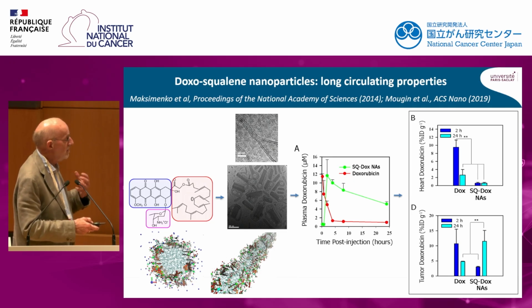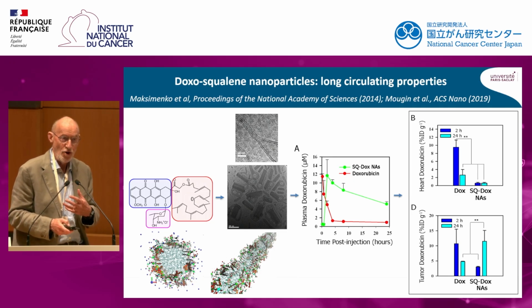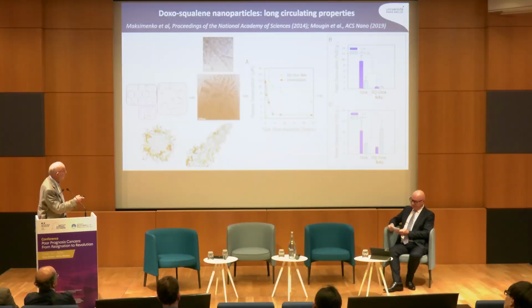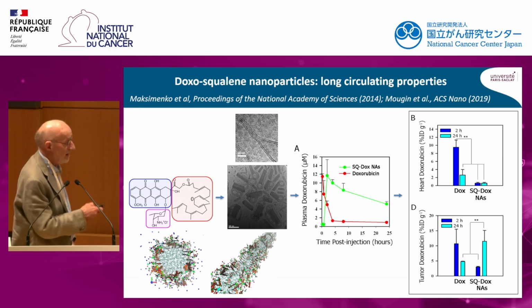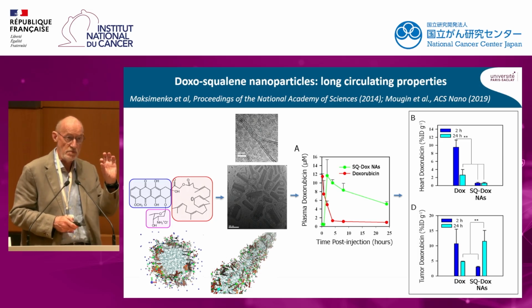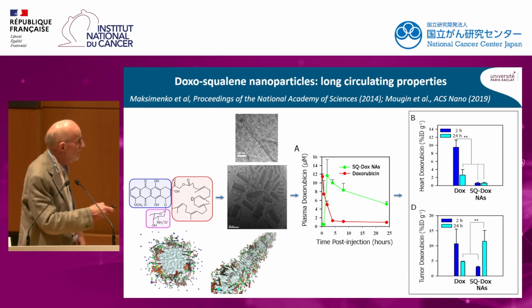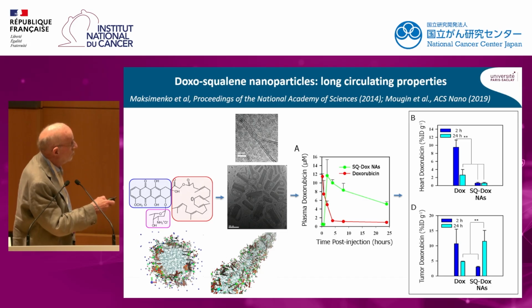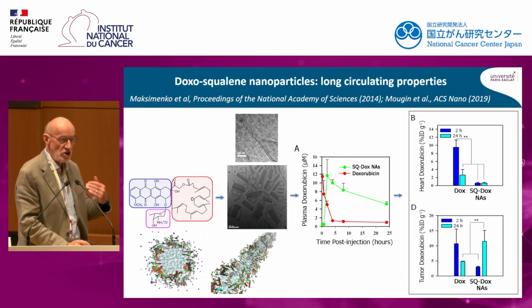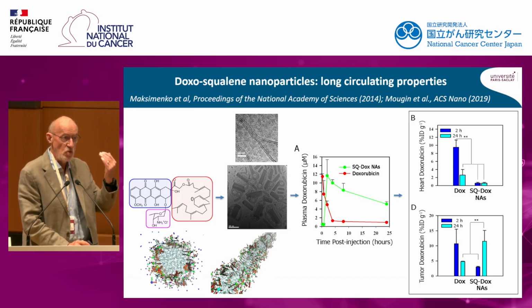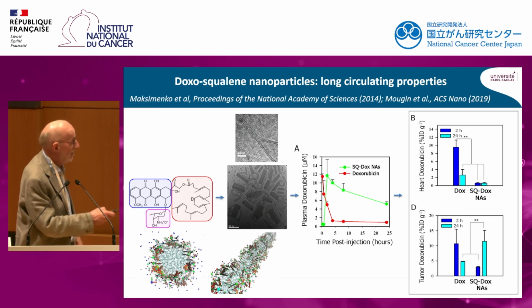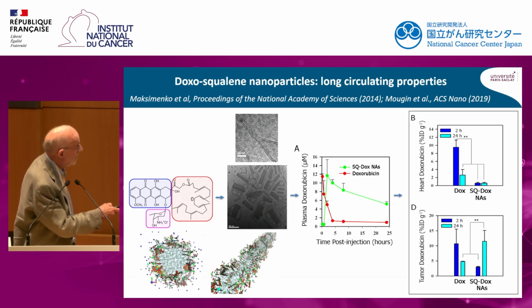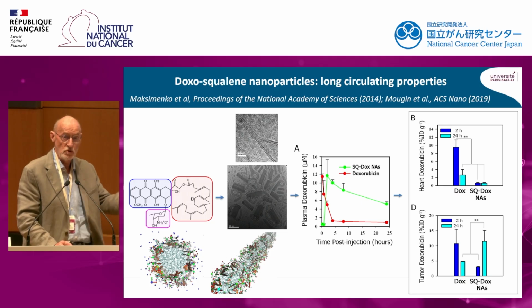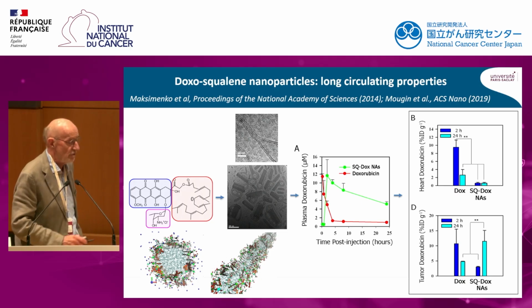And to show you that, in fact, it is a very flexible concept, we have now linked doxorubicin to the squalene, and in that case you can see that we obtained elongated nanoparticles. And after intravenous administration, this allowed much higher concentration, here in green, of the squalene doxorubicin prodrug than after administration, in red, of doxorubicin as a free drug with a very rapid blood clearance.